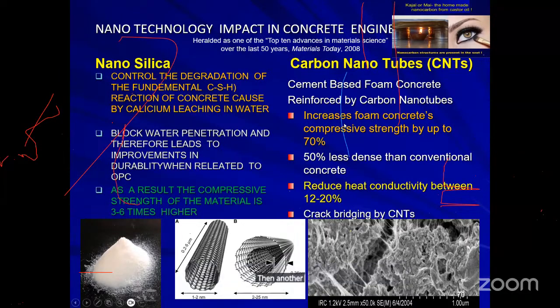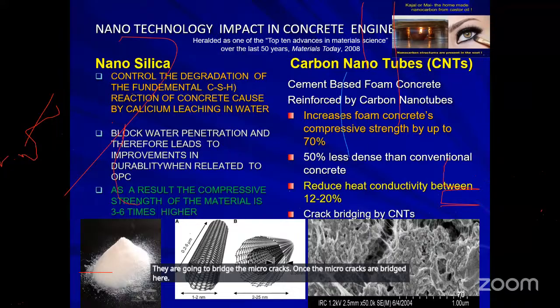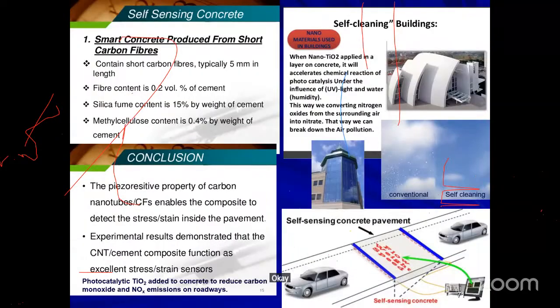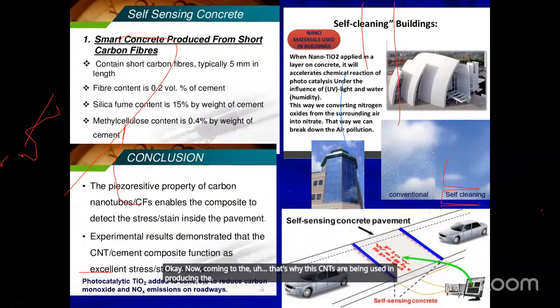Then another technology is the use of carbon nanotubes, CNTs. We can use CNTs to increase the compressive strength by about 70%. Then we can also reduce the heat conductivity by about 12 to 20%. And the most important aspect of the CNTs is that they bridge the micro cracks. Once the micro cracks are bridged, the crack widening gets delayed, so the durability of the system gets increased. That's why these CNTs are being used in producing self-sensing concretes.